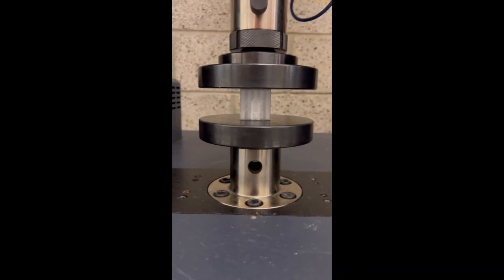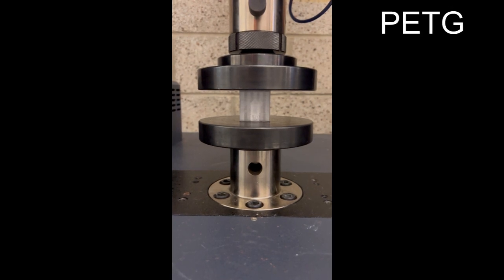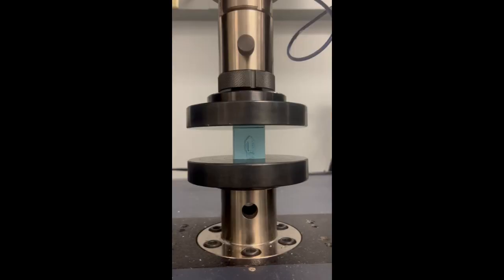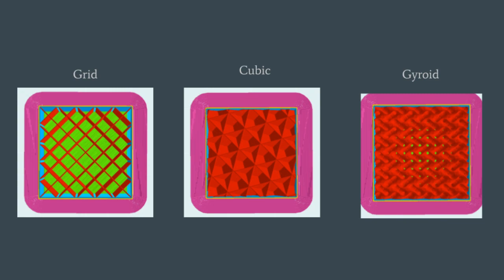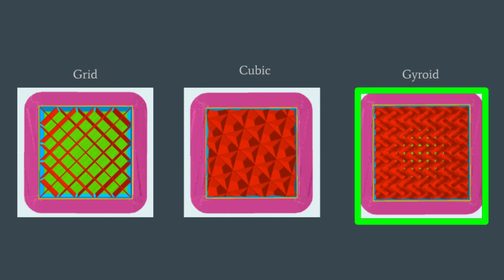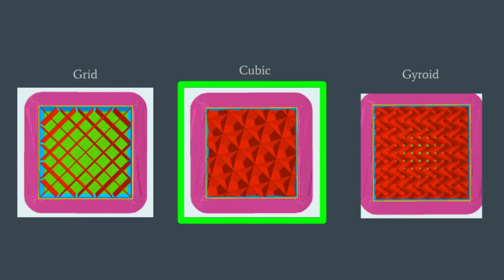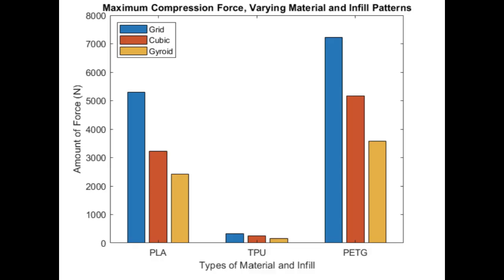In our hypothesis, we predicted that the PET-G would be the strongest material, followed by PLA and then TPU. We also predicted that the gyroid infill would be able to withstand the most amount of force, followed by the cubic and then the grid pattern. Contrary to our hypothesis, our results showed that the strongest infill was in fact grid, followed by the cubic and then the gyroid pattern. Our hypothesis was, however, correct in that the PET-G would be the strongest, followed by PLA, and that TPU would be the weakest.